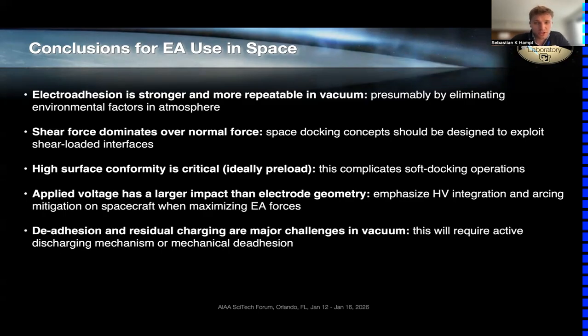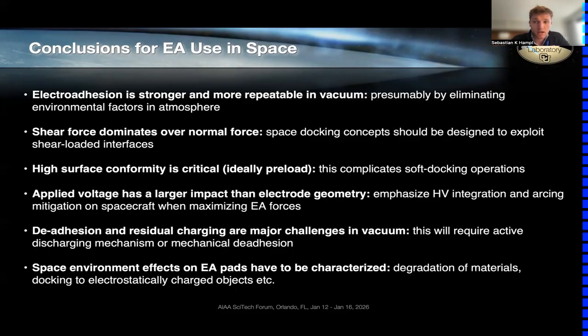And then in terms of challenges, deadhesion mechanisms and residual polarization remain a large issue because we cannot actively undock from an object without any mechanical actuators at the moment. There's no electrostatic version to force undocking, and we have seen that this residual polarization is much increased in a vacuum environment in our experiments. And lastly, it is important to characterize space environment effects like atomic oxygen, radiation, etc., on the materials that are used, the dielectric materials. Our sponsors have performed some TVAC tests that show promising results, but there is more testing that needs to be done and more work on investigating how the space environment affects electroadhesion.